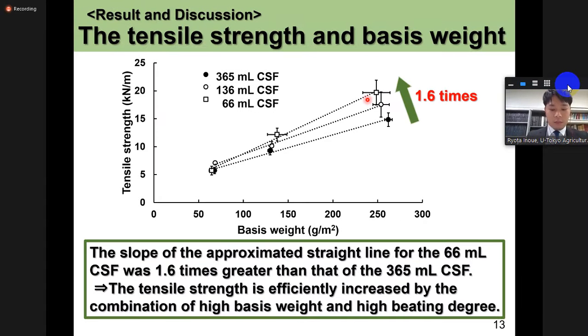This figure shows the relationship between the tensile strength and the base weight of single-layered paper prepared with different freeness values. There is a positive correlation between the tensile strength and the base weight. As you know, in the high base weight region, the tensile strength increases as the beating degree increases. What is interesting here is that the slope of the approximated straight line for the 66 milliliter CSF hand sheets was approximately 1.6 times greater than that of the 365 milliliter CSF hand sheets. The tensile strength is efficiently increased by the combination of high base weight and high beating degree.